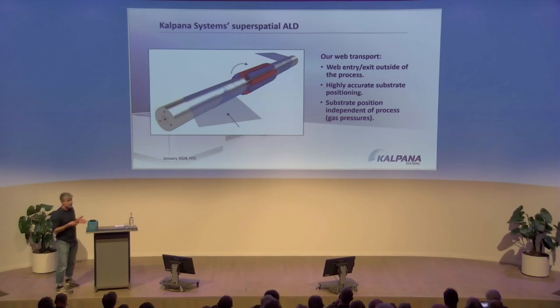And then focusing specifically on batteries, it is also important to note that the position of the battery electrode in this case is so well defined that it's independent of our process pressures, which might come in handy when you actually see that it's a challenge to supply and remove the excess gas from the porous material. You want to supply it with a high pressure and actually take it out with, at least in the exhaust, a very low pressure. And this is the only way we think you can actually coat a battery electrode fast.